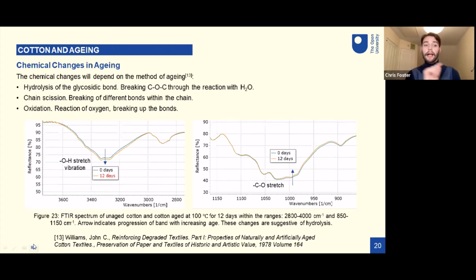These spectra that I've highlighted in figure 23 are from my own work. It just shows two spectra. The one in orange is 12 days aged cotton. The one in blue is unaged cotton. You can see that the OH vibration increases with aging, whilst the CO vibration decreases. And this could be indicative of hydrolysis being the dominant reaction in my samples, but oxidation and chain scission could also contribute to this. So next slide, please.